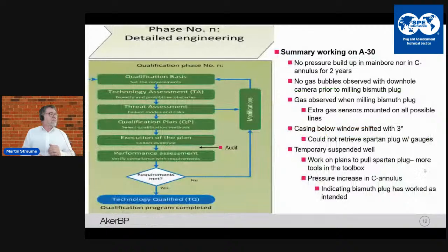During those 2 years where we had the bismuth plug installed, we did not have any pressure buildup in the main bore because we capped the top of the well and saw no buildup in pressure. No gas bubble had been seen downhole with downhole camera, and the fact that we then saw gas after we removed the bismuth was proof for us that indeed the bismuth was good when it was there, but the leaks came back when we had removed it.